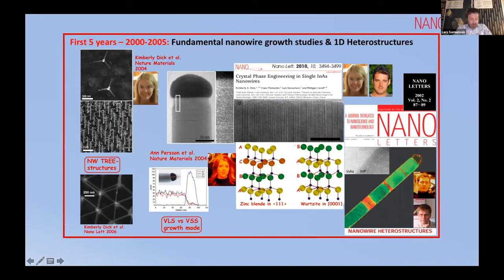So what you will be able to, maybe I should have a pointer. What you can see, I think, is a rather famous early publication. It was already in February 2002, about the steeplechase of electrons jumping over these barriers in one-dimensional devices. We also spent a lot of effort on trying to understand what indeed is controlling the growth of the nanowires, what happens at the interface between the catalytic or quasi-catalytic metallic particle or droplet and the nanowire underneath.